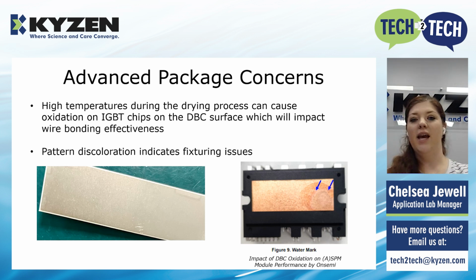So what we like to say is, while higher temperature tends to be where people will lean towards, understand how that higher temperature can affect your material set as well. Anything copper related, the nickel DBCs, those high temperatures can affect detrimentally. So understand how much heat you're actually putting into the process. Also look at how your air knives are oriented. You want those air knives to be able to sheet material and water off the surface in a relatively uniform pattern, so you don't have that pooling situation that's happening with the copper.